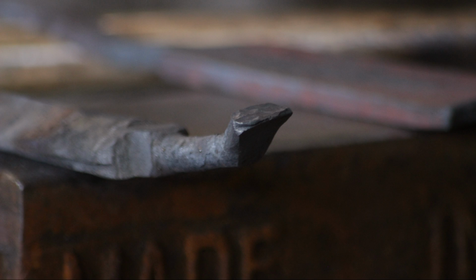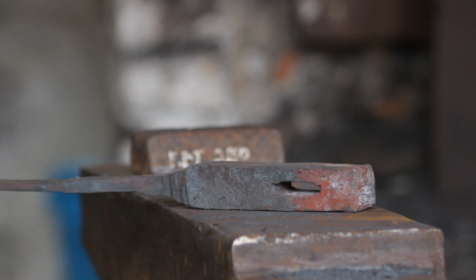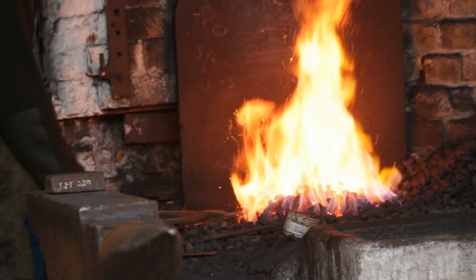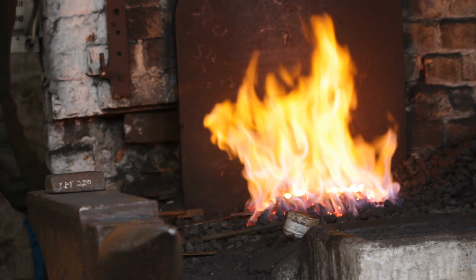you then want to start creating the material for the socket. So the sockets on these bayonets were wrought iron as opposed to the carbon steel of the blade. I'm using the tail end of a paddle rod from the canal. Now this is fairly poor quality wrought iron, and it's got a slotted eye in the middle, as you can see. So I need to weld this up.